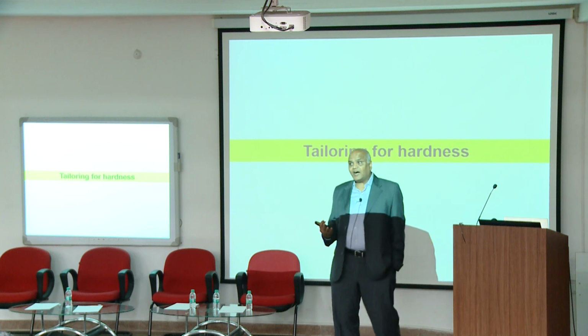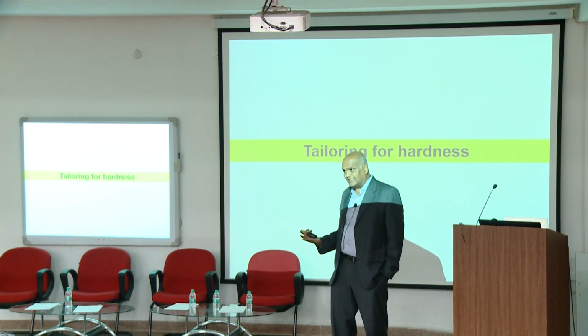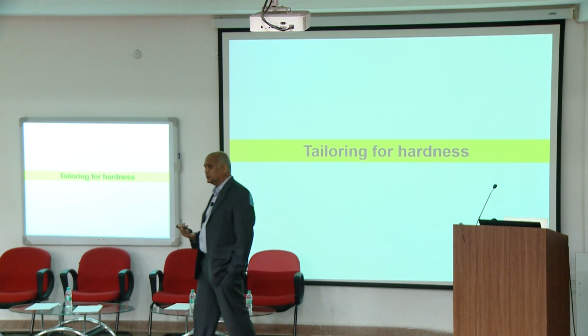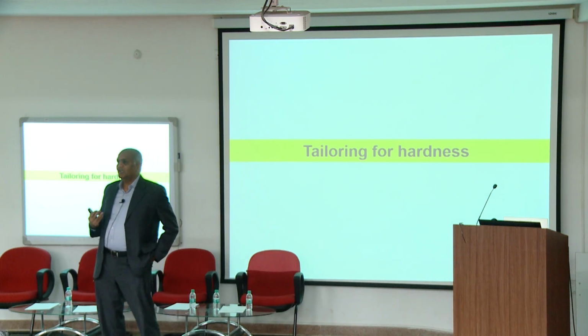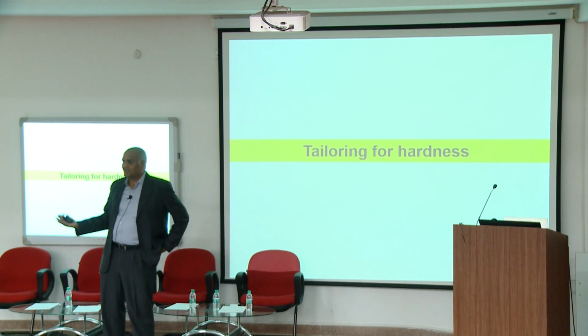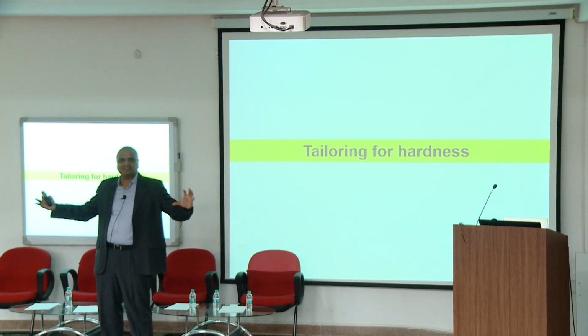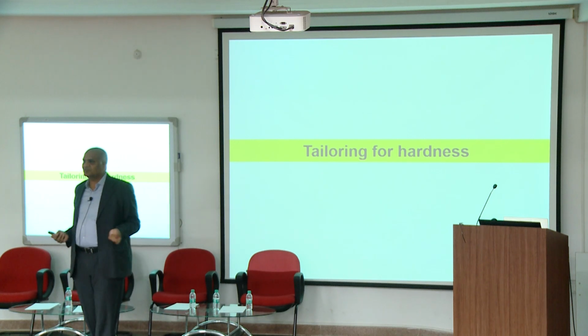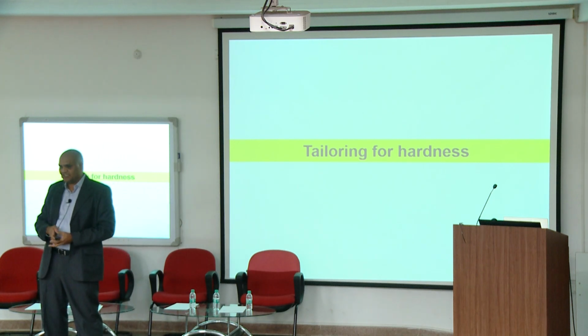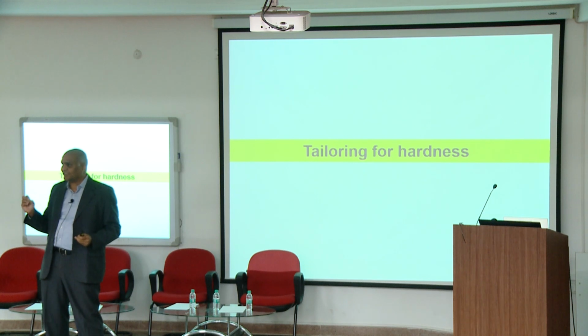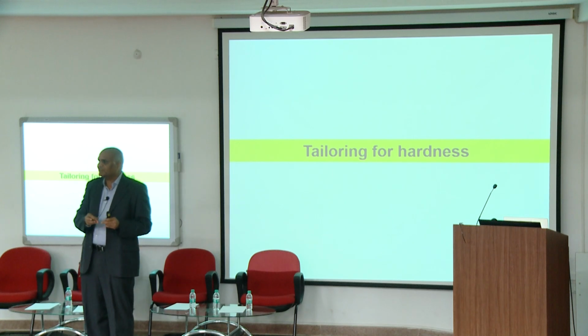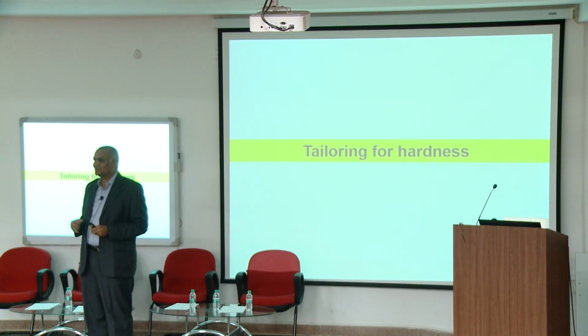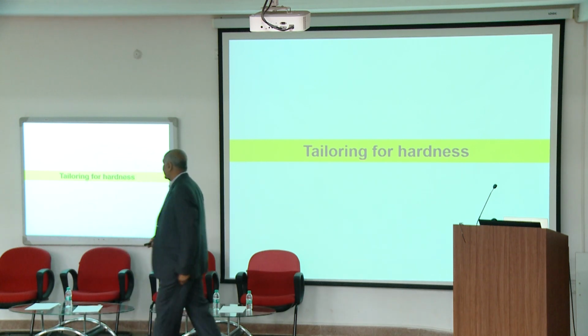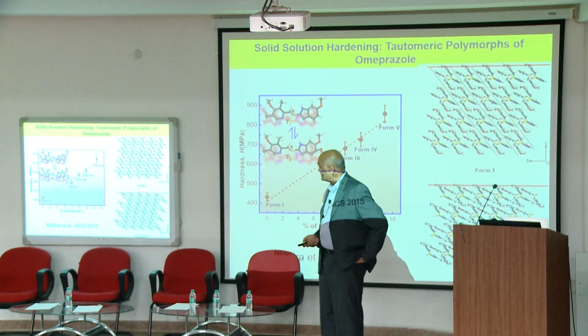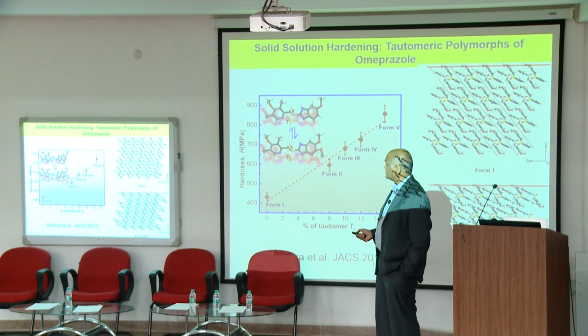Now, softer materials give you more solubility, but from a manufacturing point of view, softer materials are not good, because in Reddy's Labs or other pharma manufacturing, they grow these crystals in large vats, and then they subject them to something called micronization. They basically grind these crystals into fine things, because you need finer crystals, because if you want 125 milligrams, you should have exactly that kind of crystal. So, okay, how do you tailor hardness? This we showed with omeprazole.